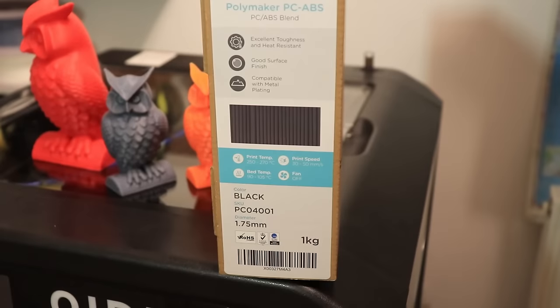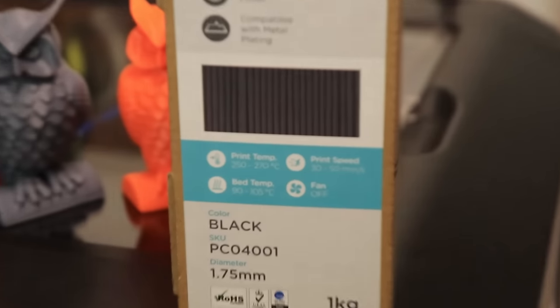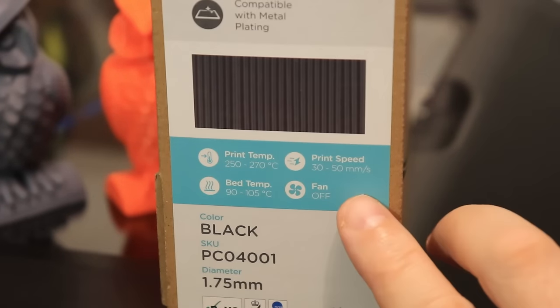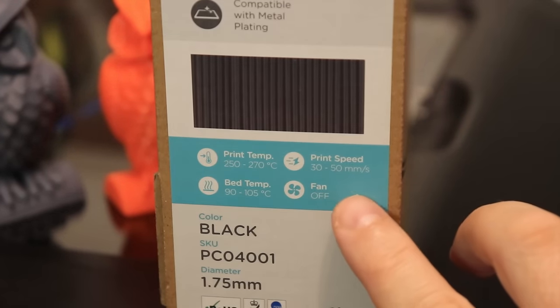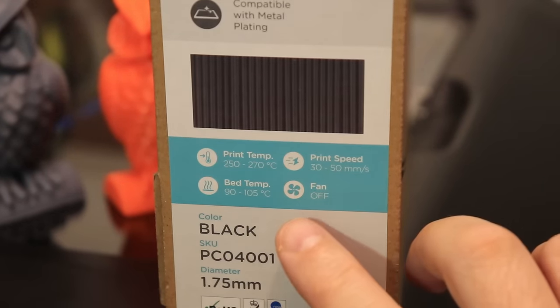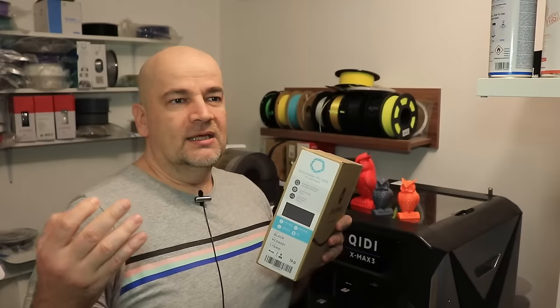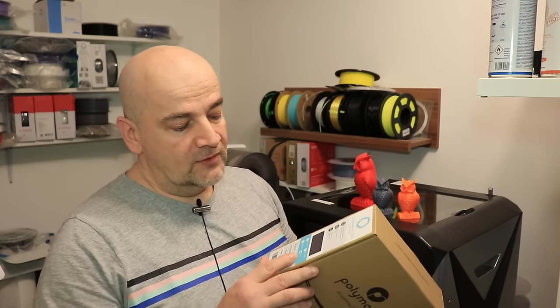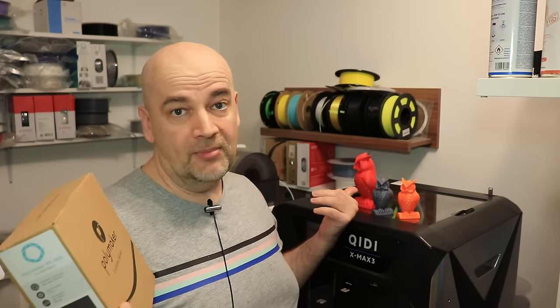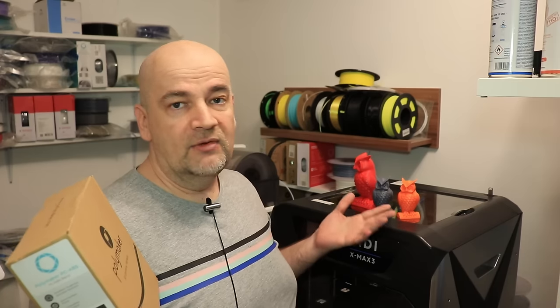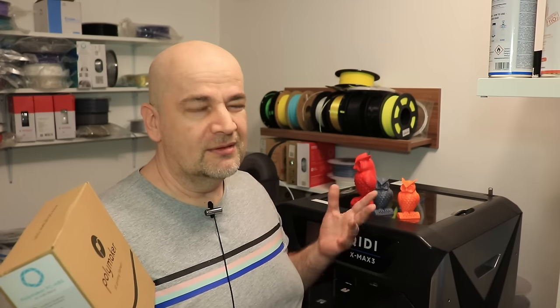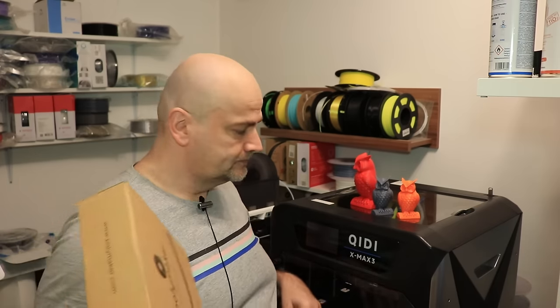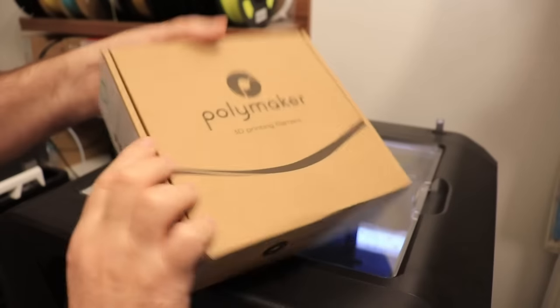According to specifications the print temperature is between 250 and 270 degrees Celsius. Nothing special about it, and the print speed is up to 50 millimeters per second. I will try to do the basic settings for ABS and I will slow it down maybe to 50% but that's also very fast. I think it's time to unbox it.